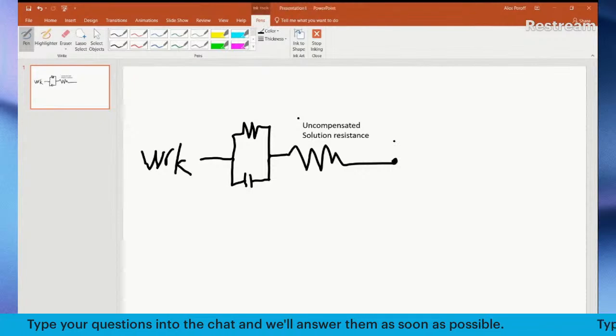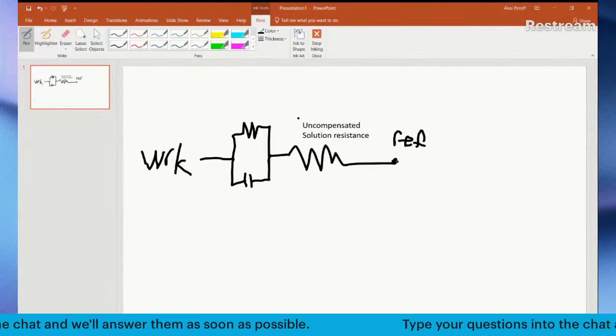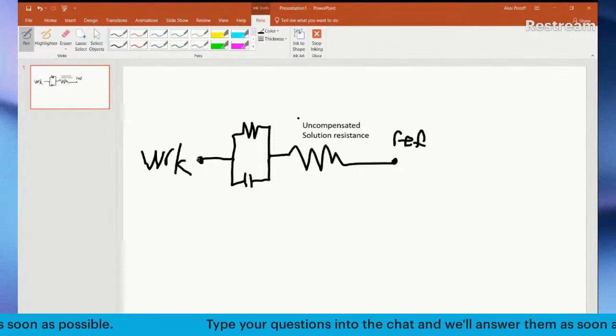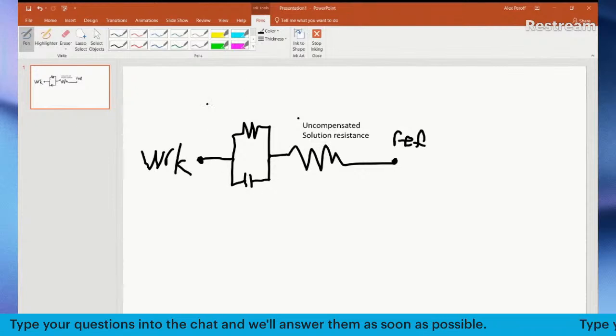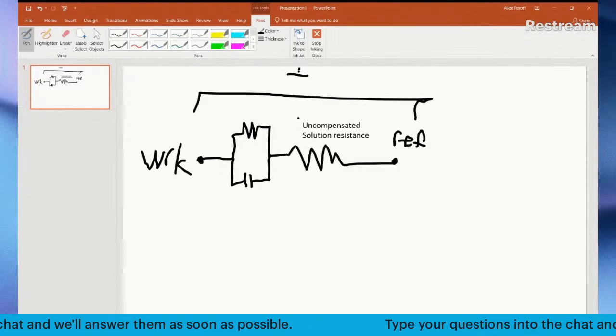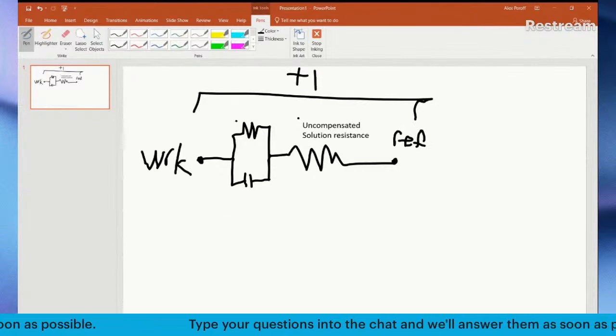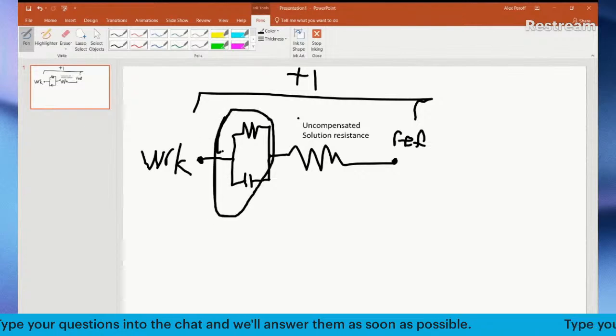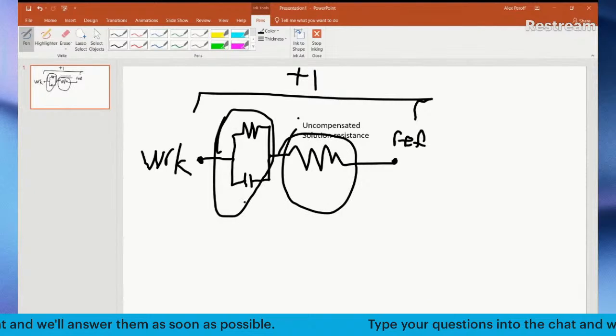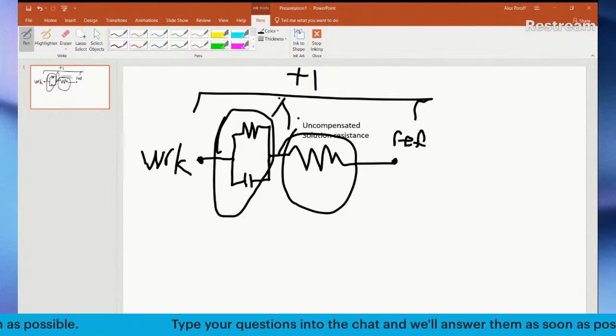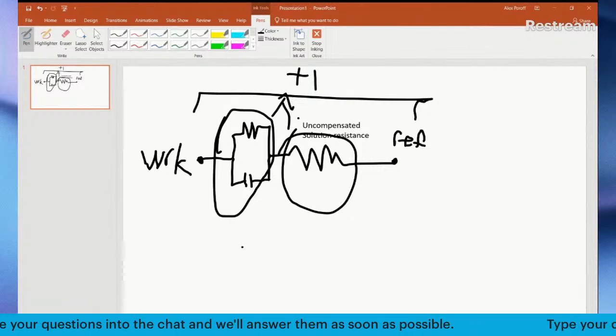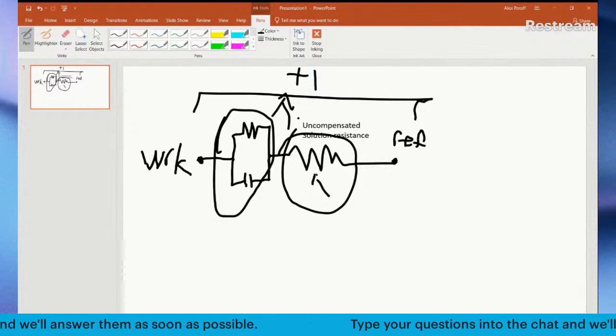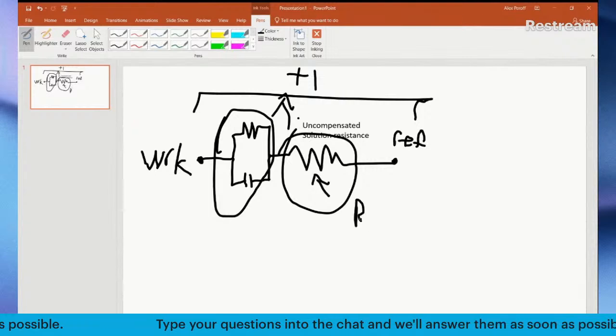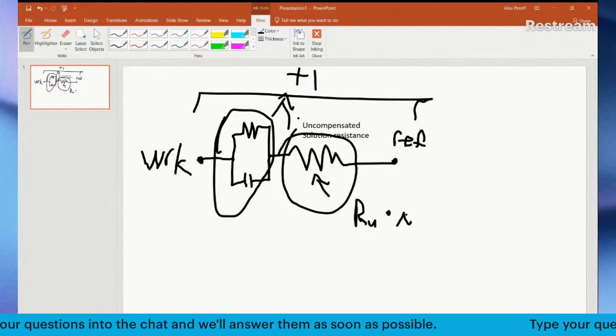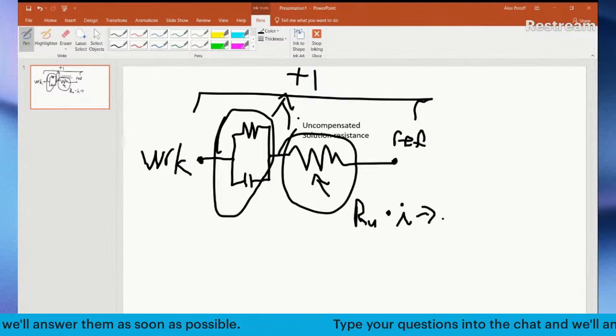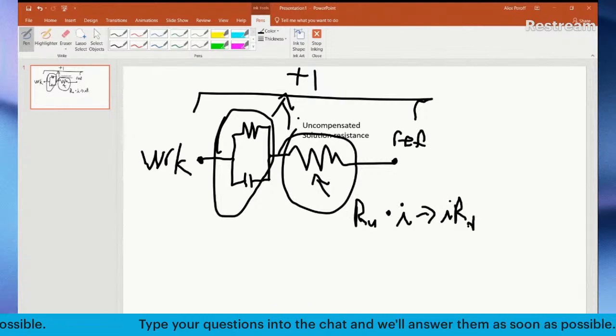And then you have your reference electrode here. This is where the reference electrode measures the potential. So you can see very clearly from this, there's two places. If I apply plus 1 volt across the working and reference electrode, there is a drop off here, and there's a value here, and both of these need to add together to get 1 volt when I'm doing an electrochemistry experiment. So this solution resistance, some Ru resistance, times the current that flows through the cell gives me what's known as my IR drop.